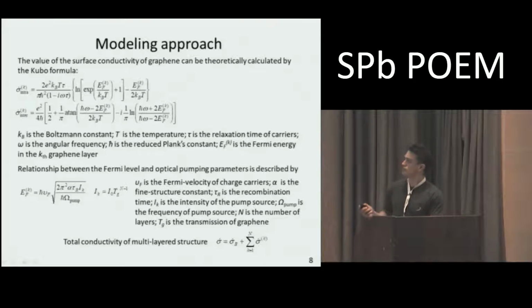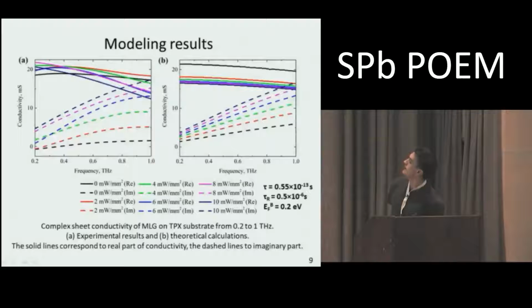So those are the results of our theoretical calculation on the right side, and we can see that the approximation definitely fits the experiment, and we can extract the parameters of our investigated material, specifically recombination and relaxation time, and the Fermi energy of the bottom layer.